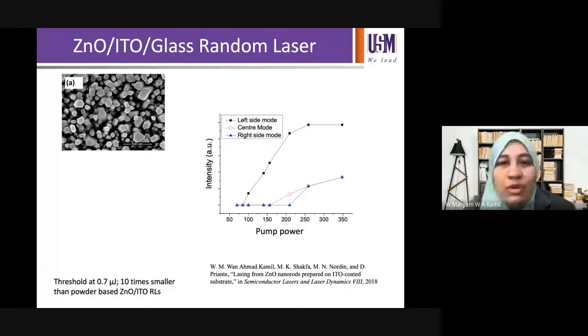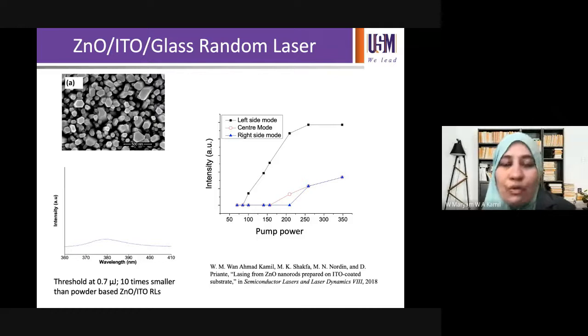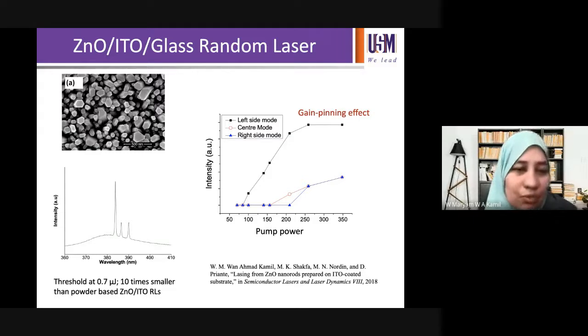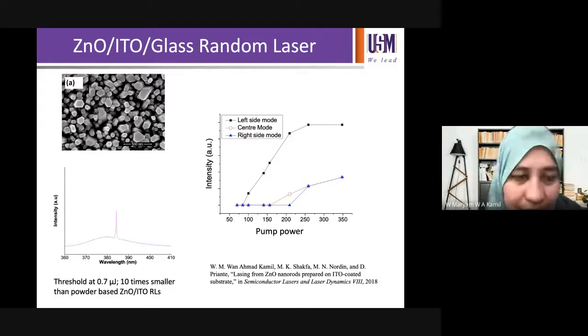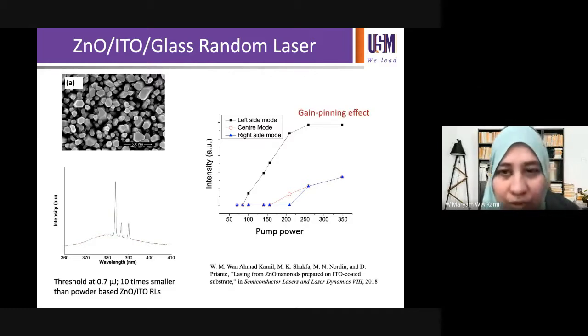Then we decided, okay, let's change a bit. Why don't we put ITO in between the zinc oxide and the glass? And what we notice, yes, there is lasing with increasing excitation power, but we still see the fighting of modes. Initially there's only one mode dominating, and then suddenly we have two other modes appearing. So these two modes appeared at higher pump power compared to this single mode.